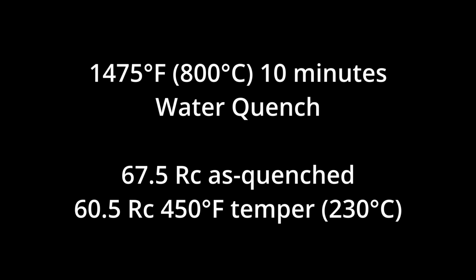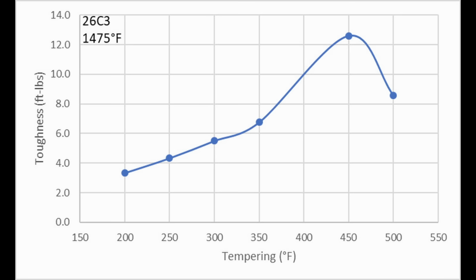If we went any hotter, we would probably start to get tempered martensite embrittlement. And when that happens, the hardness goes down and the toughness goes down. So 450 we felt was the right compromise to get the toughness as high as we could for this high carbon Wootz steel, while also maintaining some hardness and avoiding tempered martensite embrittlement.